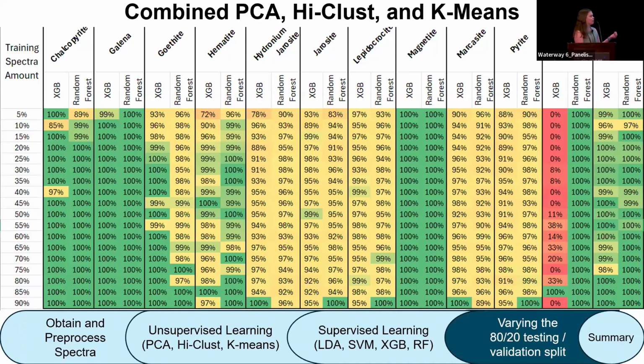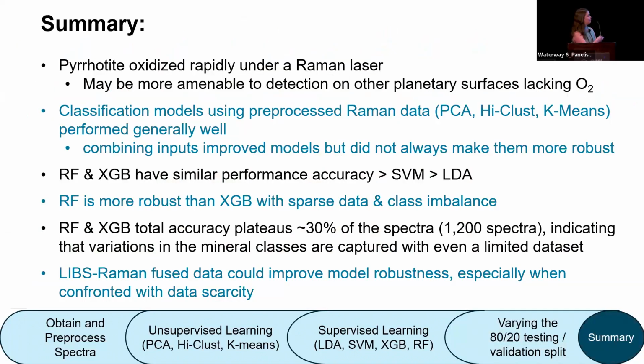So pyrrhotite is the one we actually have the least amount of spectra on because it was constantly oxidizing with the laser. We have only about 13 different spectra over it. But Random Forest was able to figure out that pyrrhotite was pyrrhotite. So pyrrhotite oxidized rapidly under the Raman laser, but with Random Forest, it worked very well.